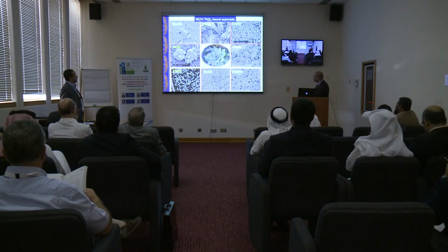The zinc material we can use as moisture sensors. Because what happens is, if you have a zinc sheet in the presence of TCNQ and acetonitrile, there is no reaction. However, when you start adding a drop of water, the reaction happens suddenly with a blue color change. This is because of the formation of zinc TCNQ with H2O. So this is why we can use this as water or moisture sensors.